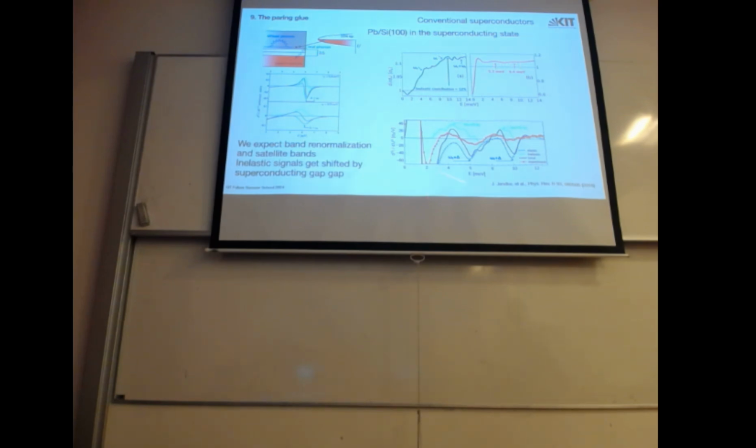So in the superconducting case, our experimental data is red. There are two contributions, elastic and inelastic. You can add them up to the total. And then you can see the agreement is kind of okay. But all of the peaks are actually shifted. These are the phonon energies shifted by delta. All of these things are shifted to the single particle spectrum, which is shifted by delta.